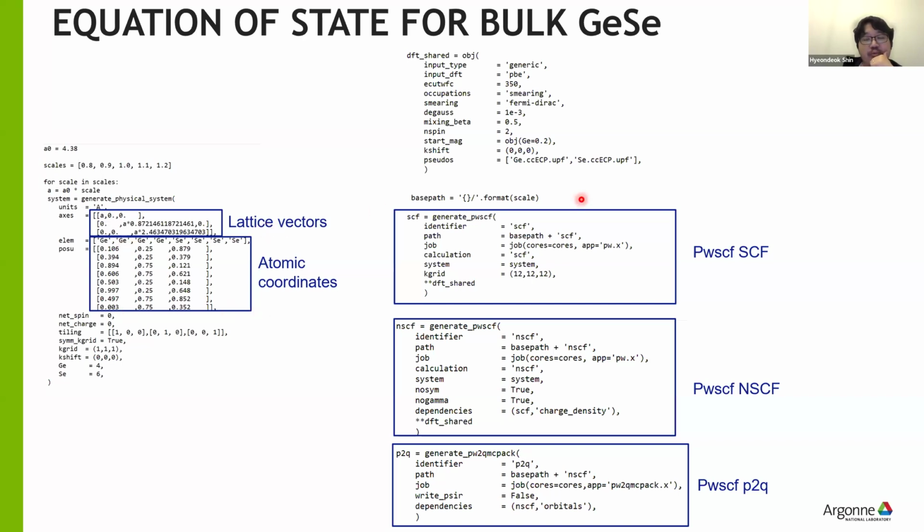coordinates. We use the plane-wave SCF calculation first with a pretty large k-point grid, and do those SCF calculations to obtain the single-particle orbitals at the desired number of twists and size of the cells. Then we convert this to use the B-spline wave functions for the QMC calculations.